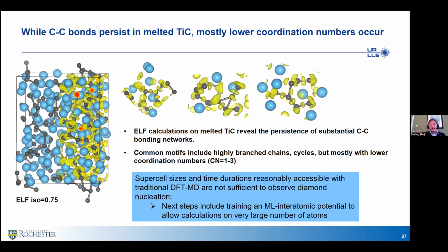When Katie calculated coordination numbers, most of the carbon bonds give you a coordination number from 1 to 3. Remember, for diamond the coordination number needs to be 4. So we don't see that here. Even though this is hundreds of atoms in the simulation box, it's still too small for nucleation to happen or to be well simulated. So the plan is to use such QMD simulations to train a reliable interatomic potential. Then you can use the machine learning potential to do a large-scale simulation with millions of atoms. That might make it possible to see if diamond nucleation can show up in such a system or not. That's the next step she's going to do.